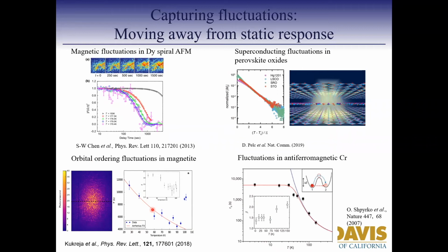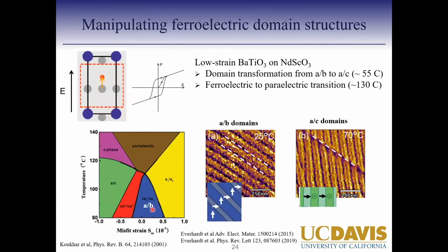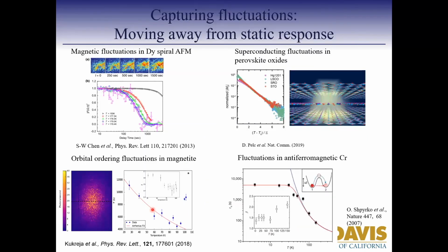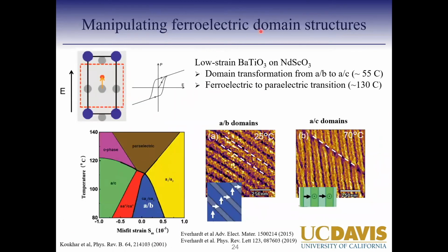And then as you get to the phase transition, these fluctuations can either get faster or slower, depending upon the mechanism of the transition. So we looked at fluctuations in ferroelectric domains, and ferroelectric domains are different from these magnetic domains, which happen because you have ordering in the electronic structure. In this case, ferroelectric domains occur because you have ordering in the crystal structure.